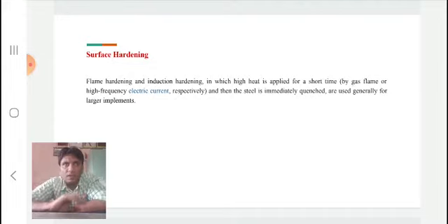So, in flame hardening, a gas flame composed of a single or multiple flame heads moves across the surface of the part, raising the temperature up to 850 degrees centigrade, followed by a water quench head that sprays water at the surface previously heated. There is a choice of fuels, for example acetylene, propane, or natural gas. The flame head can be static and the part moves at a predetermined speed in another process variation.